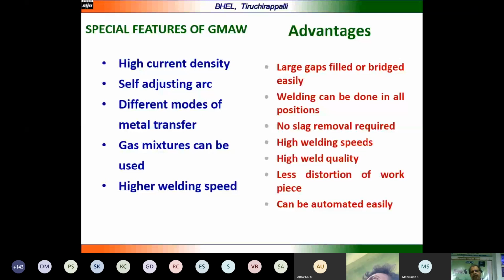Advantages of the process: large gaps can be filled or bridged very easily. Welding can be done in all positions. No slag removal is required if it is solid wire. If it is a flux core wire, there will be a small amount of slag that has to be removed. Higher welding speeds can be achieved, as I told earlier. The weld quality will be higher, there is less distortion of the workpiece, and it can be automated easily. Most of the robotic welding machines in the world are working on the GMAW process. That way we can see that actually.